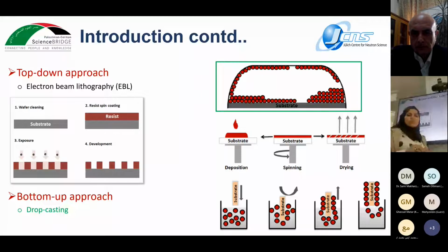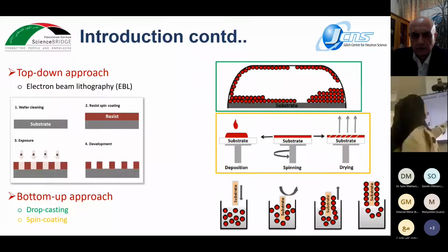The second method that we use in the bottom-up approach is the spin coating method, where we use a simple instrument called a spin coater. We mount our sample in this spin coater, where we have to control the rotation speed and the rotation time. And once we mount the sample in the spin coater, we deposit our particles above the wafer until the solvent evaporates.